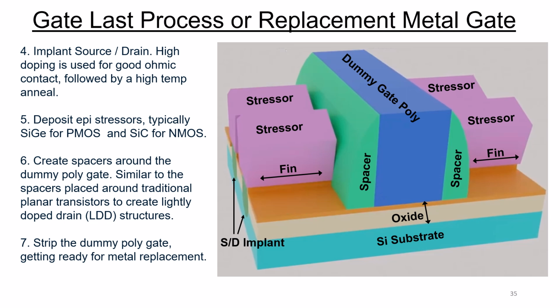Step number 4 is to implant the source and drain regions, and we use high doping for good ohmic contact, and that's followed by high temperature anneal. Now it's hard to see the source and drain regions in this particular drawing, they're underneath the stressor material, but you can kind of see the implant off to the side here. Again, the fin is running left to right here. It's running underneath the stressor and the poly gate. So we'd be implanting the source drain regions on the left of the gate and on the right of the gate.